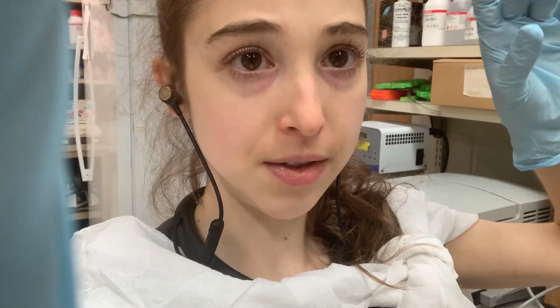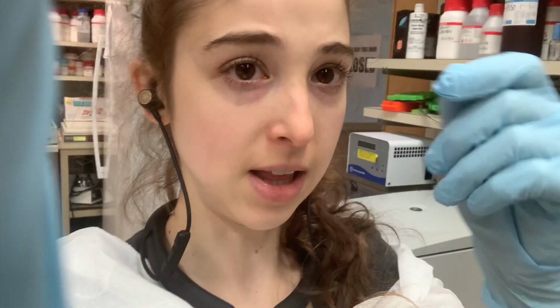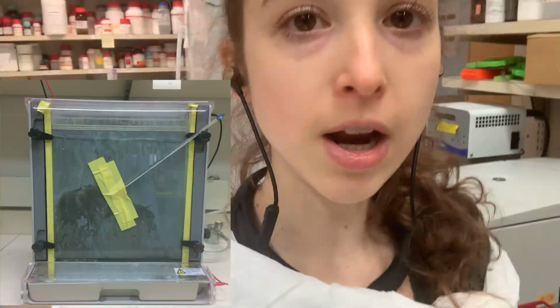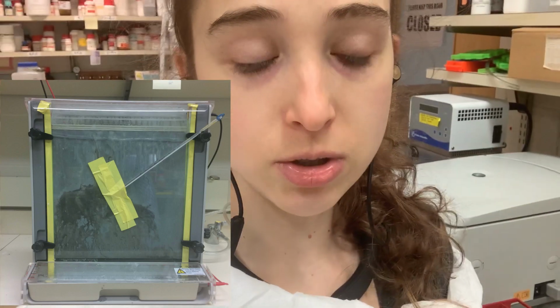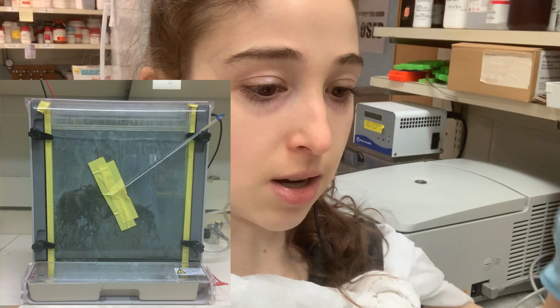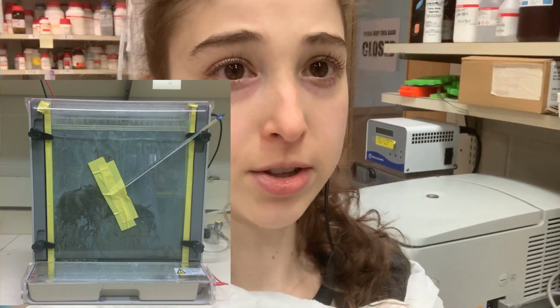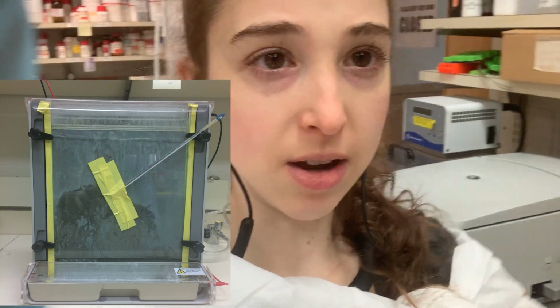but after a little shaking, so you don't get pockets that are polymerized and others that aren't. You want to make sure it's mixed, but you don't want to introduce bubbles while mixing. Inverting up and down a few times typically does the trick. For some types of gels, you really need to avoid bubbles, like sequencing gels, urea gels, those really big ones that are really thin. In those cases, you can degas it, where you have a filter device and you spin it to get out any bubbles.